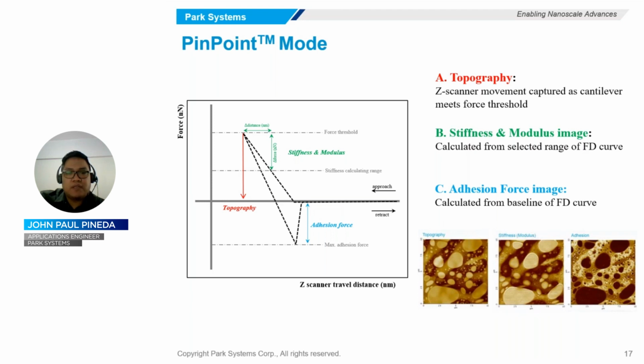So in pinpoint mode, these properties are acquired at each pixel in the entire imaging area and displayed as an image. Below is just an example of the topography and mechanical data acquired from a polystyrene and soft polybutadiene sample.